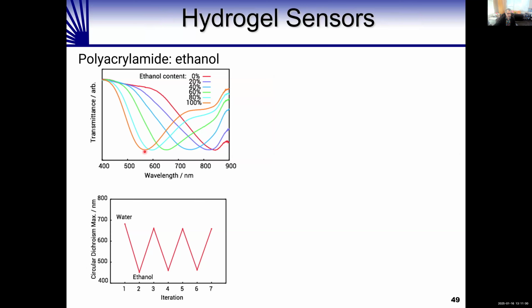If you put it into pure ethanol, it doesn't swell at all, and it still reflects light around 550 nanometers. But if you put it into liquids that contain increasing amounts of water, you can see that the reflection redshifts across the spectrum. So to our naked eye, we can detect the color of the film, which correlates with a particular concentration of alcohol in the water, and we can use these for reversibly sensing the concentration of alcohol. Just to let you know, this ethanol is the alcohol in vodka and other alcohols that people drink.